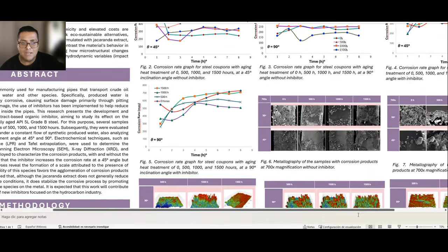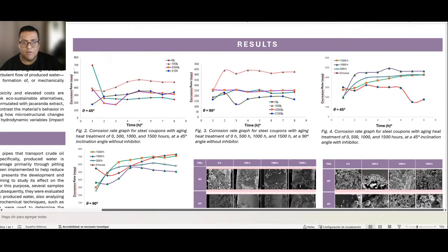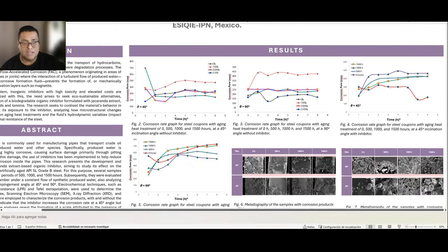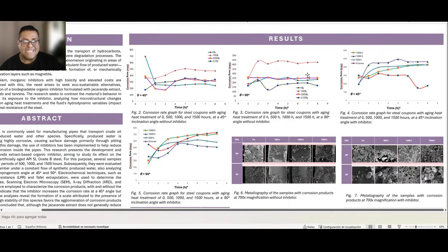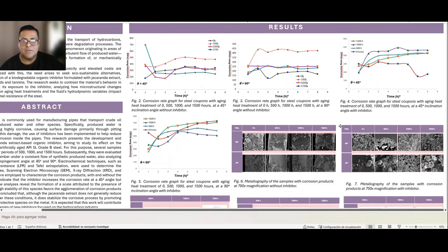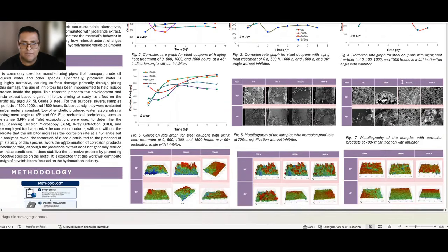Now, a look at the results. The linear polarization curves revealed something very interesting. The steels aged for 500 hours show the most critical deterioration rates and oxidation areas. Surprisingly, when we constructed the data, we discovered the Jacaranda inhibitor systematically increased the corrosion rates compared to the tests without it. For example, the sample at a 45-degree angle went from 312 MPY without the inhibitor to 605 MPY. However, despite increasing the attack, the inhibitor managed to stabilize the speed over time by promoting the rapid formation and agglomeration of surface products.